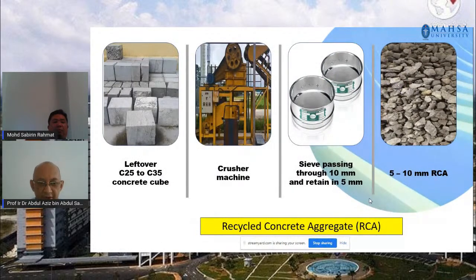Now, this is the recycled concrete aggregate that I was mentioning just now. We have all these concrete cubes left over in our laboratory, and we happen to have a concrete crusher in our lab, and this concrete crusher will crush these cubes and make them into small pebbles. What we did was we looked for a size between 5 to 10 millimeter of RCA. We are going to use that size, and of course we have to use a sieve to make sure that we obtain the size that we are looking for in terms of the recycled concrete aggregate. So it's a lot of work. The process takes a bit of time.